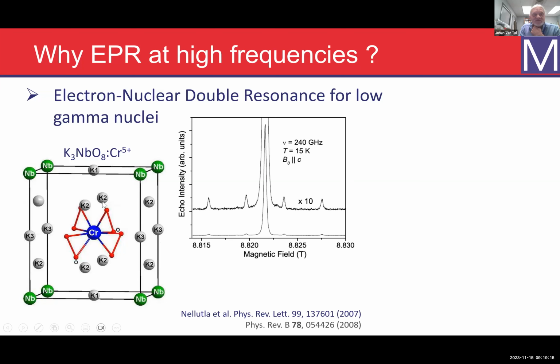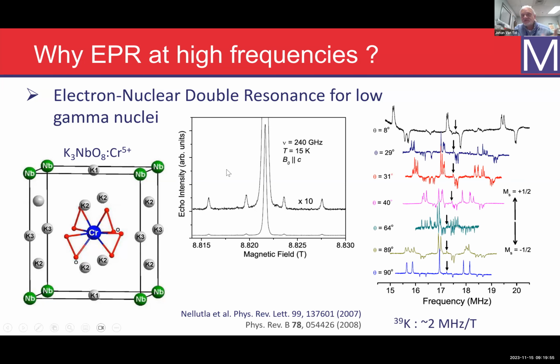But you don't see all the interactions with the potassiums that are surrounding this center, or the niobiums that are surrounding this center. And you won't find too many examples of potassium ENDOR. I actually had a very hard time finding any examples. But this has a nuclear Zeeman splitting that corresponds to about 2 megahertz per Tesla. So at X-band frequencies, this would be like 0.6 megahertz or so. And these are difficult frequencies to measure. So if you do this at 240 gigahertz, the nuclear Zeeman frequency is much higher. It ends up at around 17.5 megahertz. And then you can really resolve the ENDOR and you can see the individual lines.